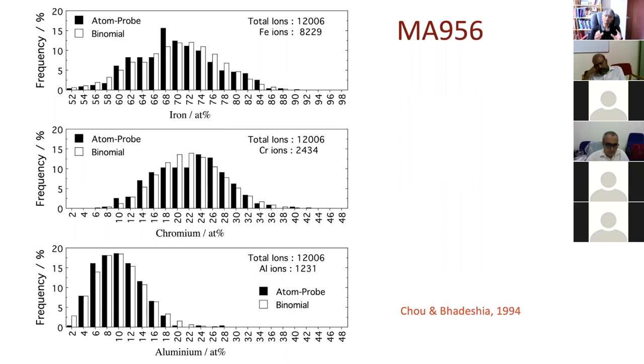And of course, the iron-chromium system is the classic system where you get spinodal decomposition at around 475 degrees centigrade. So it should not be a random solution. Indeed, you can repeat this experiment after holding it at a temperature within the spinodal for a long enough time, and you will see separation into chromium-rich and iron-rich regions. So the way to decide whether or not the atoms are distributed at random is to compare the chemical composition of small clusters of atoms against what you would expect from a binomial distribution.